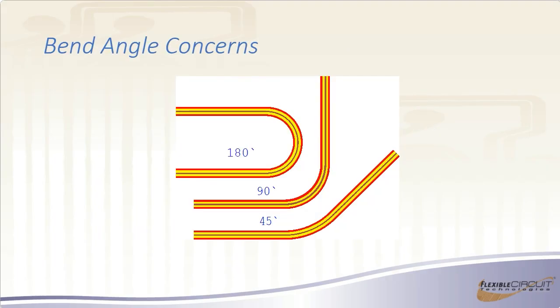Bend angle can have an impact also. I can tell you that if you bend something at 45 degrees, it's almost impossible to damage a flex circuit regardless of what your bend radius is. You're just not bending it far enough. It's usually around 90 degrees that we start seeing issues with bending if you have a stack up that doesn't support the bend, and at 180 it can become even more pronounced.